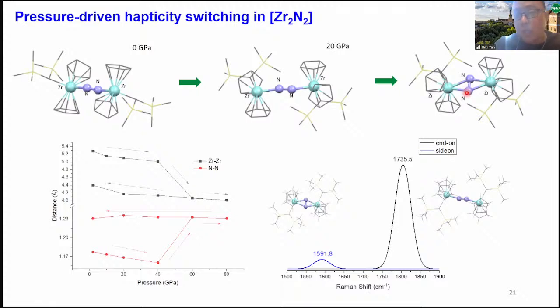So the DFT calculation only tells us there's a possible new ground state at high pressure lying out there - it doesn't tell us how to get there. So my graduate student Cindy went on to do the experiment. She synthesized this crystal, loaded it in a diamond anvil cell, put it under pressure, and then measured the Raman spectrum. This is a busy slide, so let me walk you through it.